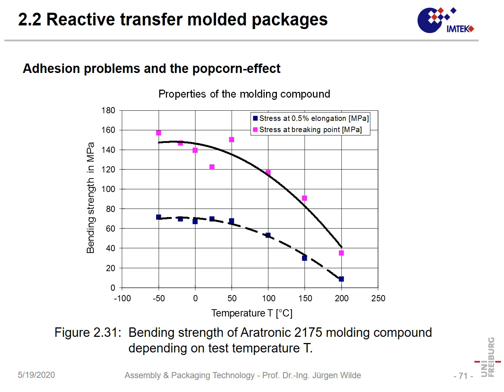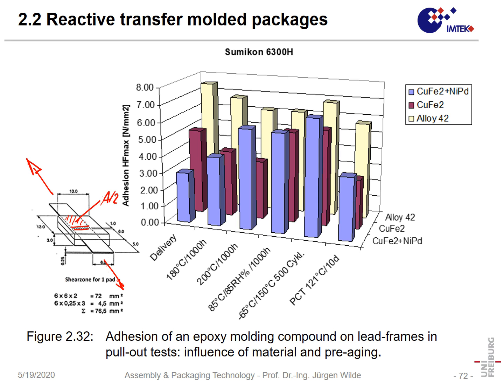For instance, it has a fracture strength of roughly 140 megapascal at low to intermediate temperatures, and then it degrades over temperature. Also, the yield point is significantly lower, but still that's a little deformation in the material of 0.5%. Also, this yield point will go down. So we can say the polymer itself is quite strong. It's really strong, even compared to other materials like metals. And on the other hand, we measured this adhesive strength here. And here we made the experiment where we had different lead frame alloys. We had alloy 42, we had copper iron 2, and we had nickel palladium, which is equivalent to nickel gold.